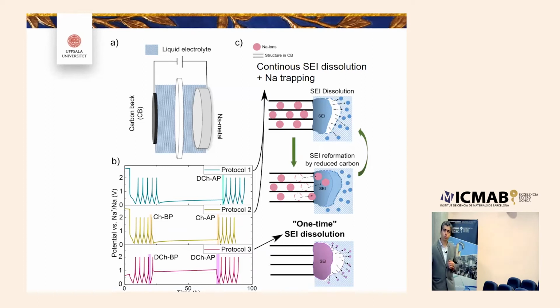We have also been doing this pause experiment at high potential, at 2 volts for example, where the battery goes by itself down to almost 1 volt. That means there should be no SEI formation at such a potential—there we can look at only and only SEI dissolution.